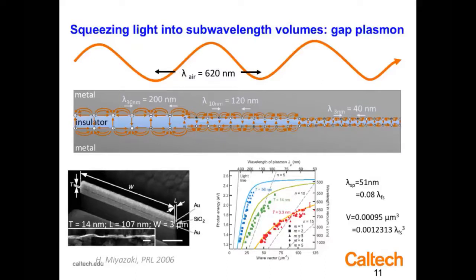This is the really revolutionary idea behind nanophotonics, that we can actually change the dispersion properties of light. This creates a cavity where the wavelength is now 8% of the wavelength in free space. If I made a cavity with this little gap plasmon, it has a volume of 1/1000th of a cubic wavelength in free space. If I made a free space cavity with metal mirror walls, it would be 1 cubic wavelength. This is 1/1000th of that in size. And we'll see with graphene, we can go down to 1/1000000th or smaller cavity size, the smallest cavities that have ever been made.